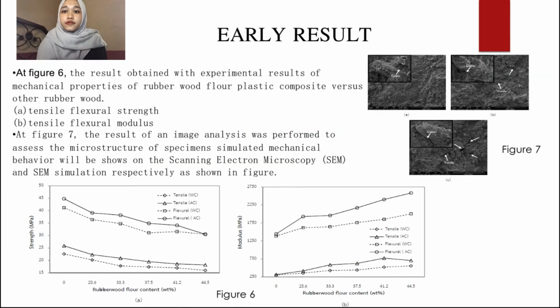For the early results, in Figure 6, the experimental results of the mechanical properties of rubber wood flour plastic composite versus other rubber wood are shown: A for flexural strength and B for flexural modulus. Figure 7, the result of an image analysis was performed to assess the microstructure of the specimen. Simulated mechanical behavior will be shown in the scanning electron microscopy SEM and SEM simulation respectively, as shown in the figure.